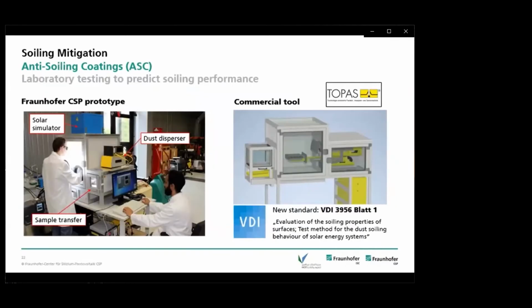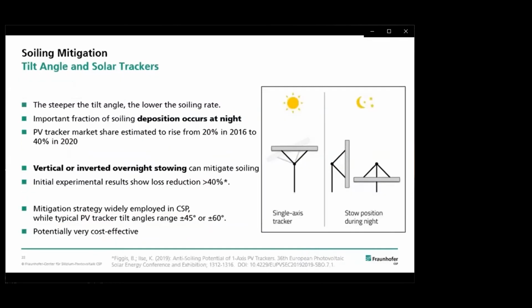In order to design these coatings, we also used laboratory soiling experiments with a new test setup which we designed and which is also commercially available, together with standard for soiling testing, the VDI 3956. Another approach could be the change of tilt angles and the use of solar trackers. It is known from literature and many outdoor experiments that the steeper the tilt angles, the lower is the soiling rate. And also an important fraction of soiling deposition occurs during night.